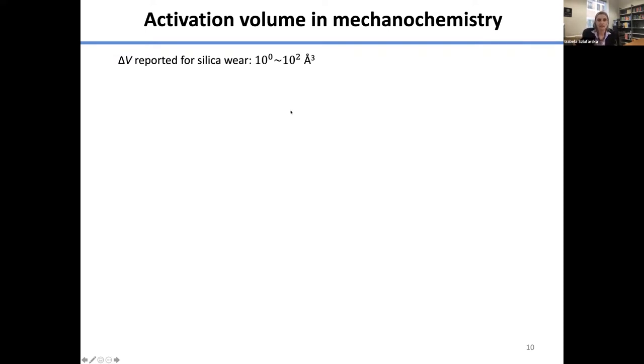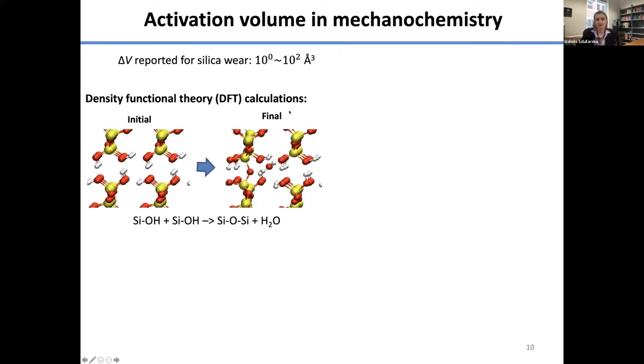We looked in this case at silica-silica interfaces because these are the interfaces that are studied. There were a lot of experiments reported on that, so we could compare. And these are quantum mechanical calculations based on a technique called DFT. But it's basically quantum mechanical calculations where we put surfaces together. The surfaces have a known chemistry, in this case, passivated with these OH groups. And then when they come together, they form this strong silicon-oxygen-silicon bond. This is called a siloxane bond. And friction is now proportional, we have shown before, to this number of strong bonds across the interface. So if you form these kinds of covalent bonds, this tells you how friction is going to increase.